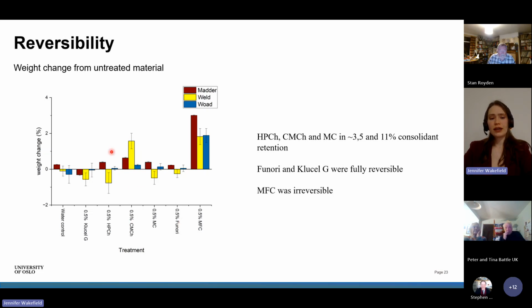What's very interesting is for the carboxymethyl chitosan, the one that we saw the color change with the weld, particularly for the weld, that weight hasn't gone back down to what was before it was treated. So for some reason, it seems to be holding on a bit more when the weld dye is present than with any of the other dyes, which warrants further investigation. It's kind of interesting, but not particularly relevant. The point is that it is retaining that and it's not fully reversible.